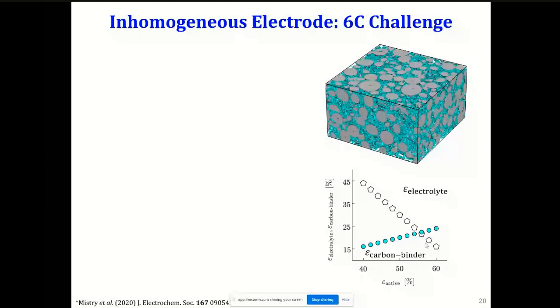So during that process, they would attach to the locations where there is more active area, more area between active particles and the solvent that you use for drying. And that is going to be more where you have more active material volume fraction. So that's why you would simultaneously have more carbon binder phase wherever you have more active material volume fraction. So you see it's sort of positively correlated. And then the porosity would exhibit an opposite trend.